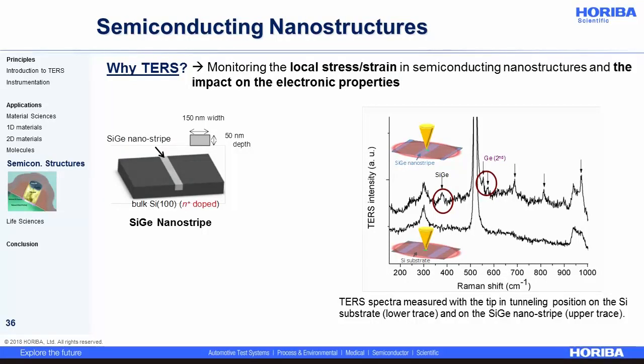We see the very intense silicon phonon band, located at 521 centimeters minus 1. And then on the upper part, we see that when the tip is above the silicon germanium nanostripe, some new bands are amplified and appear. Here we are concentrating on monitoring the silicon germanium Raman band that is roughly located at 380 centimeters minus 1.